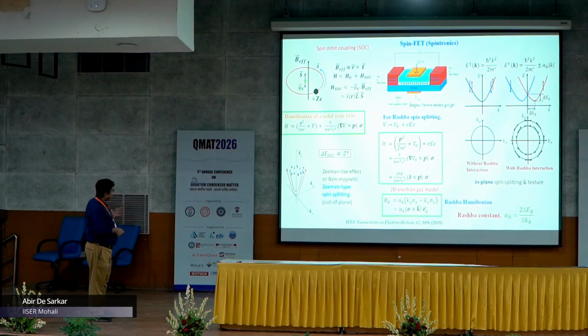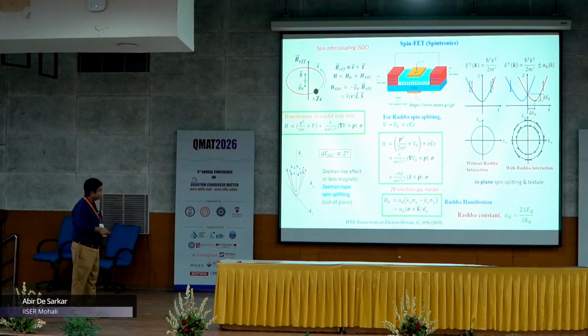Now, on top of that, if you apply an electric field along the z direction, the potential changes from this to that, and that introduces an additional term in the Hamiltonian. This is the Rashba Hamiltonian, and what it does is that it lifts the in-plane spin degeneracy in these parabolic bands. So, one parabola splits into two parabolas.